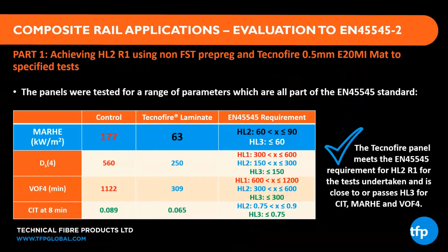So these are the stage 1 results comparing performance of the non-FST, the non-fire smoke and toxic fume performance rated monolithic prepreg laminate as the control to the same laminate incorporating a 0.5 millimeter layer of Tecnofire E20MI. And I just want to focus on the MARHE, the maximum average rate of heat emission, highlighted there in blue on the first line of the table. So why is heat release rate important? Heat release rate is a critical measure of fire performance of a composite, as it assesses how much energy is released by the laminate, which feeds the fire, and how quickly this energy is released. So a low number is good, meaning a relatively slow growing fire, and conversely, a high number is bad.